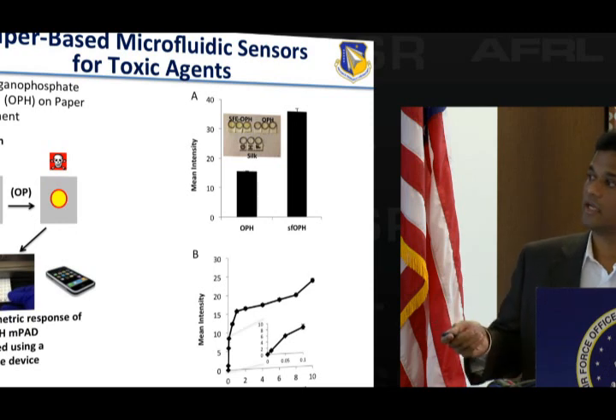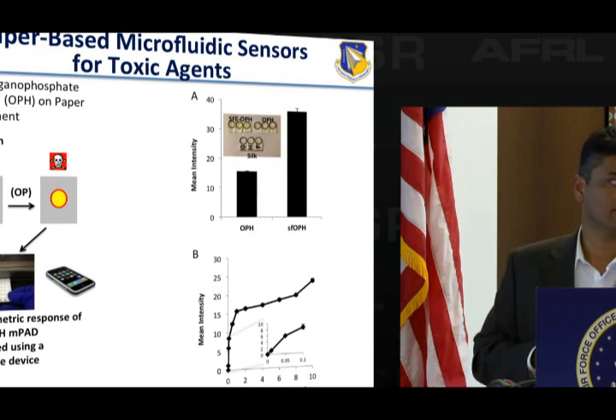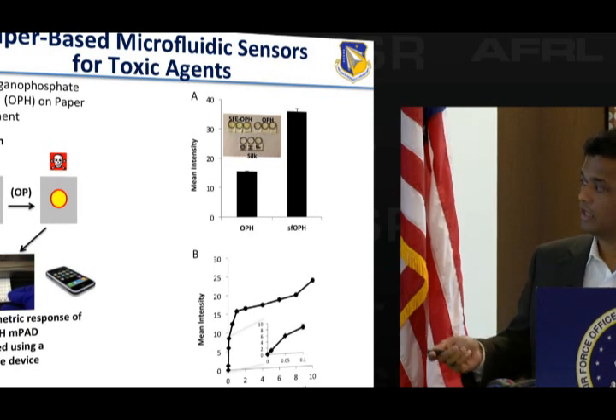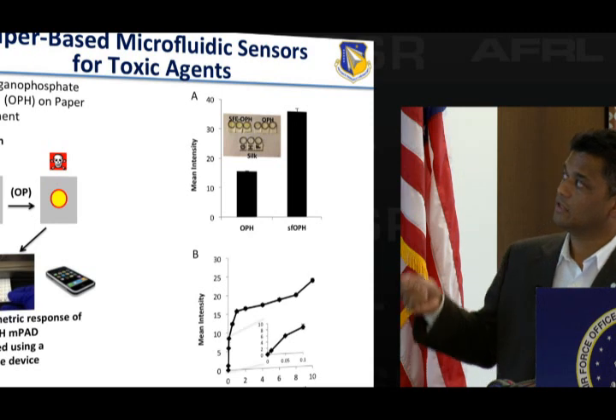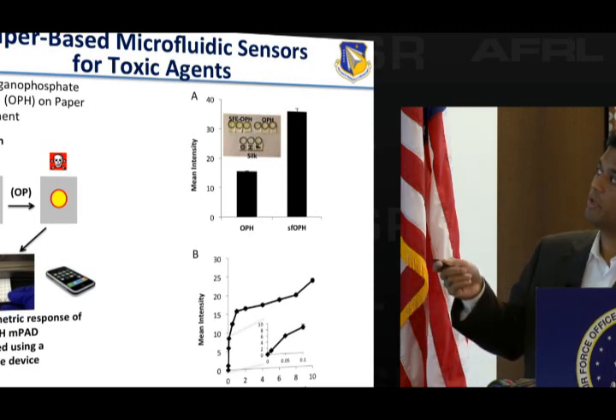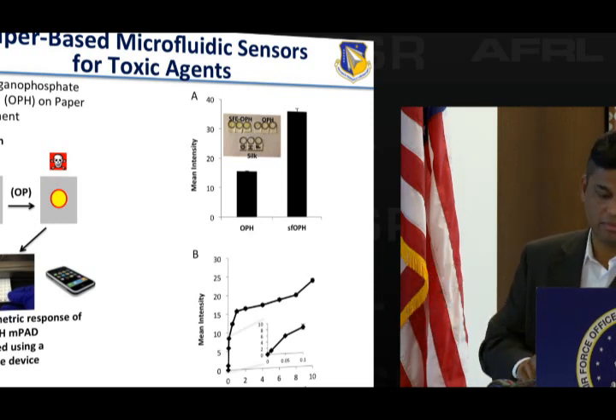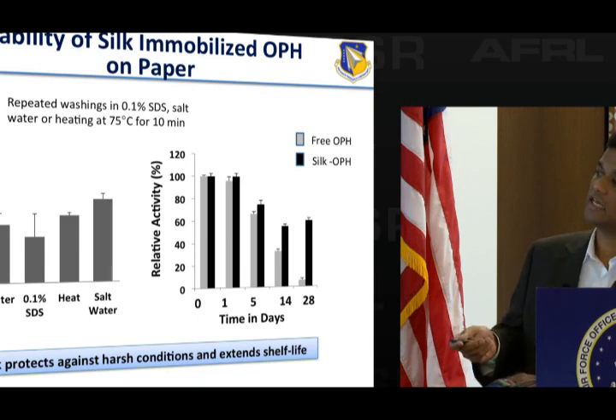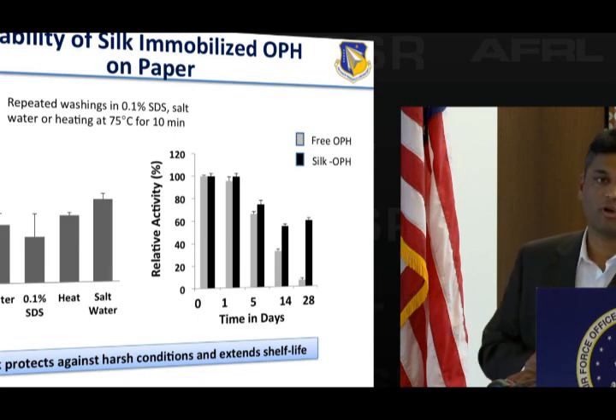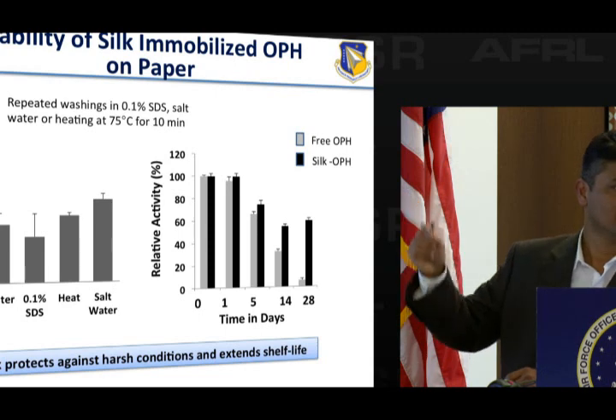Okay. So you can use a flatbed scanner if you want, or even a cell phone, take an image, and you can measure the intensity of the yellow color, and you can back calculate what is the concentration of OPH in the environment. And we've been able to show that you get very nice detection capabilities up to about 25 micromoles, and the enzyme that's immobilized onto the paper is much more stable than the free enzyme. And if you really want to do some testing, we put this in brackish salt water from the aquarium that we have. Did the assay under that.